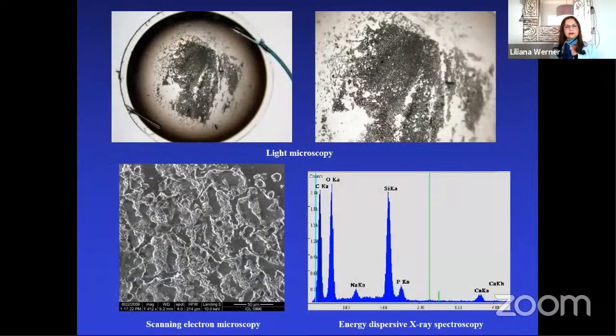Here is another case that was analyzed under scanning electron microscopy and energy dispersive X-ray spectroscopy. You can see the peak of silicon, an element that is in the composition of the lens material itself, as well as peaks of calcium and phosphorus, which constitute the main composition of the calcified deposits.